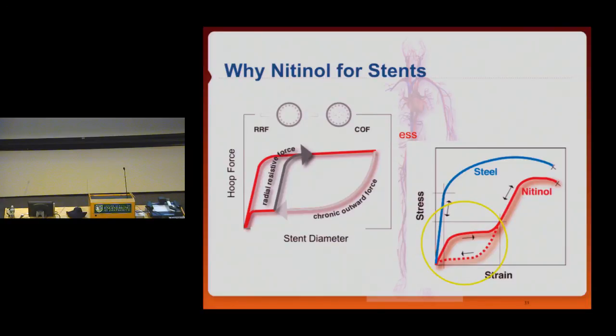But when you then try to compress this stent, say through outside forces or external forces or through a spasm or whatever, when the vessel wants to contract, the stent would oppose this force with this stiffness. So it's much stronger when it's actually being deformed. So that's what we call biased stiffness or path-dependent stiffness. Here's another important aspect. Because this unloading curve is so flat, you have a lot of tolerance in terms of how much you oversize. It doesn't really matter if your stent is 2 millimeters bigger than the vessel or 3 millimeters bigger. The force it exerts is not much higher.